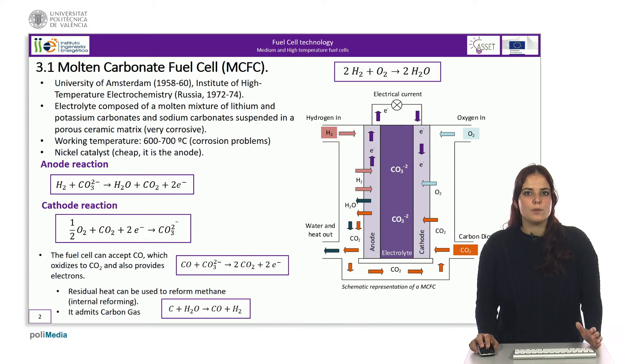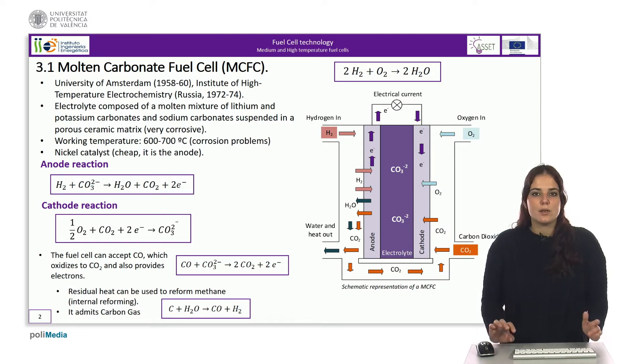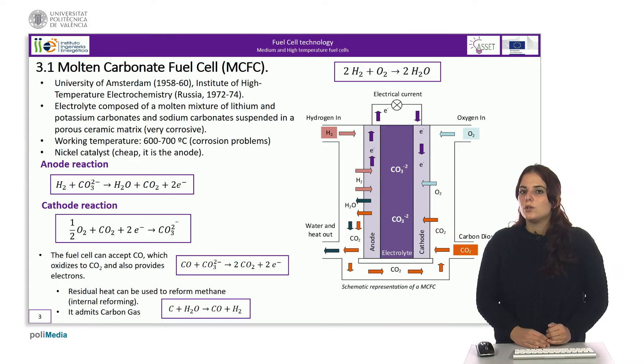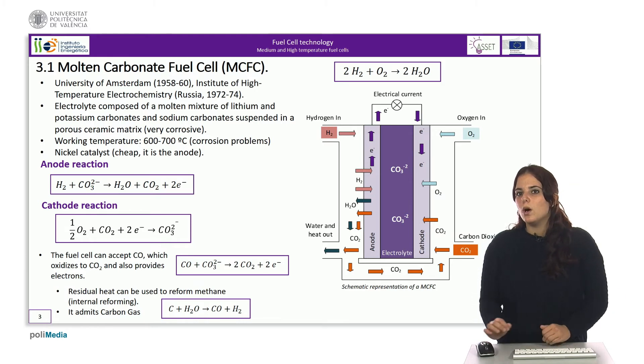The cathode is made of nickel lithium oxide, as in the case of the alkaline fuel cell. Nickel oxide is a semiconductor that, when doped with lithium, increases its conductivity tens of times. The anode is made of nickel. The thickness of the anode ranges from 0.8 to 1.5 mm, for the cathode from 0.4 to 1.5 mm, and for the electrolyte from 0.5 to 1 mm.